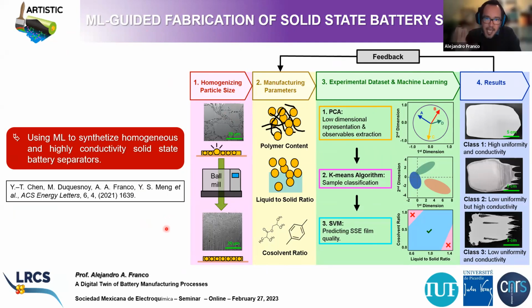We applied the same machine learning pipeline in order to predict how different manufacturing parameters are going to impact the conductivity and uniformity of solid-state separators for solid-state battery applications. The combination of algorithms that we have used is PCA, which is principal components analysis, a very nice technique to reduce the parameter space of your experimental data set. Then we use K-means, which is an unsupervised machine learning technique, in order to unravel different classes.